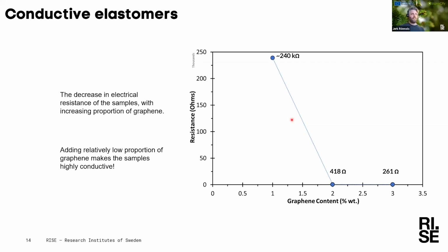And we can see that in the case when we have 1% graphene, we have very high resistance. If we want a conductive material, we want a very low resistance. So at 1%, it is to some extent conductive, but it has a very, very high resistance. But when just adding another percent of graphene to it, the resistance drops significantly. It looks like it's close to 0 here, but on this 1000 scale, it's 0.4 thousand, so 418 ohms, and adding even more graphene reduces it further. So that is very interesting. We want to be on this bottom end of this graph. So we can see that adding graphene makes this conductive, and one could think of a million interesting applications of these. I will leave it to your imaginations for the time being.